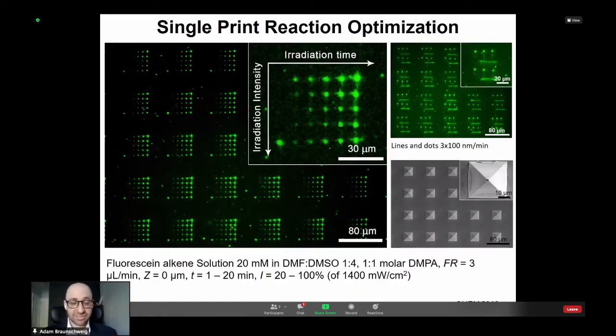Before I show you the multiplex printing, I just want to show you this concept of accelerated discovery on the surface, which is, in our view, now the only way to study reactions on surfaces. What this print is, we took a single one of our fluorescently labeled alkenes, and we wanted to study different reaction conditions. Here you see we are varying both the reaction time, the irradiation time, the amount of light we shine on the surface, versus the irradiation intensity. And what you see is the yield, which is correlated to fluorescence, increases with irradiation time, but counterintuitively decreases with the irradiation intensity.